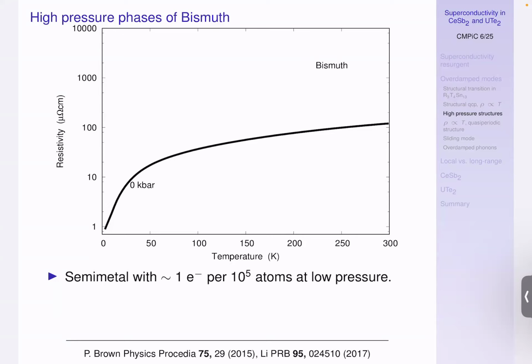Or, and I think that's perhaps an interesting question to pursue, is it actually the electron-phonon scattering itself which produces the damping? Because there will always be lower energy electron excitations that you can make. The softening comes from the fact that we get a structural transition. So that just means, almost by definition, that some phonon, some distortion mode has to go to low frequency. The question now, which I don't really see, is why would that be strongly damped? The simplest explanation could be impurities. Phonons will scatter from impurities.